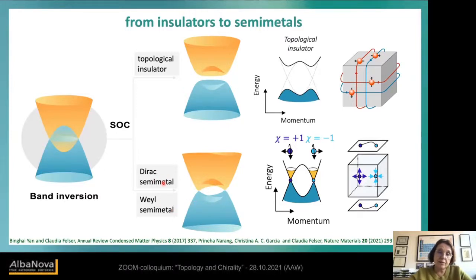So Dirac semimetals, you have this crossing point, this degenerated point at a high symmetry point. If we draw the band structure, we most of the time draw the spaghettis along high symmetry points. But in Weyl semimetals, they sometimes appear at non-high-symmetry points, because Weyl semimetals have no inversion symmetry, or they have time reversal symmetry broken, so the symmetry is reduced from Dirac to Weyl.